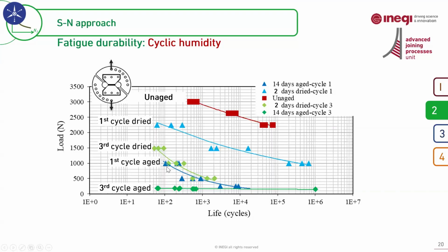And when we dried the sample, we could recover the properties by nearly 50%. And we noticed the recovery is also a function of the number of aging cycles. The recovery after the first cycle could provide us this SN curve, but after the third cycle, we have just this green one. And we believe that if we continue aging for more cycles, it will be difficult to have even a good joint after drying and recovering the properties.